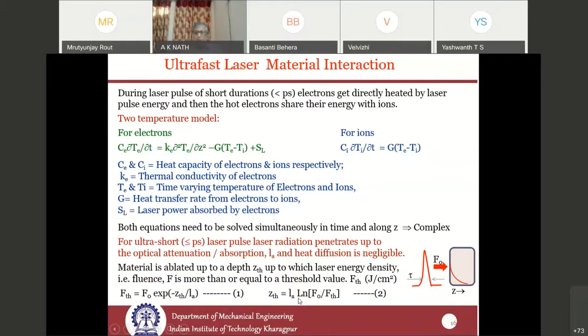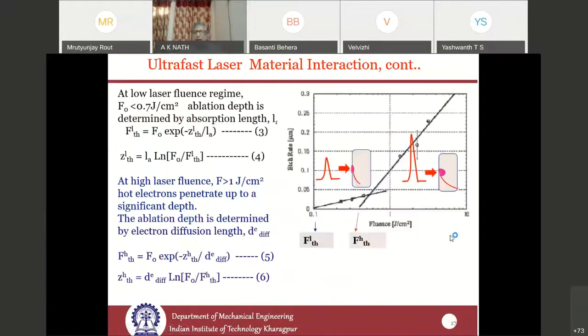But when we consider very high intensities, we found that there is a certain amount of hot electrons that cause diffusion inside the material, and this process is also very fast. Therefore, instead of optical attenuation length, here the depth is governed by what is called the electron diffusion length.